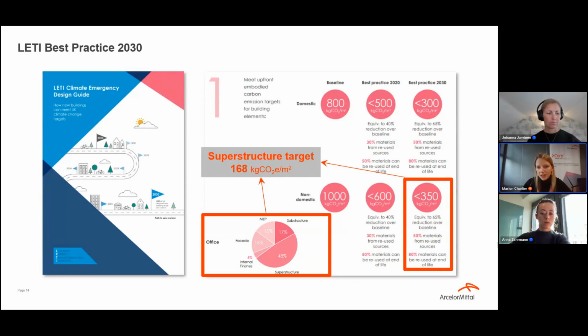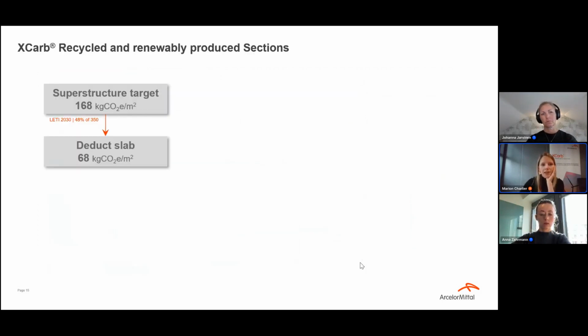So also, if we have a look at the little chart at the center of the slide, we see that, for example, for an office building, roughly the superstructure accounts for half of the emissions. So going from these 350 kilos of CO2, we take half, and we have this target of roughly 170 kilos of CO2 equivalent per meter square. So if we start from that, we deduct the slab as a first step that we assume to be at roughly 70 kilos of CO2 equivalent per meter square. And we see that for the frame, we have an allowance of roughly 100 kilos of CO2 equivalent per meter square.